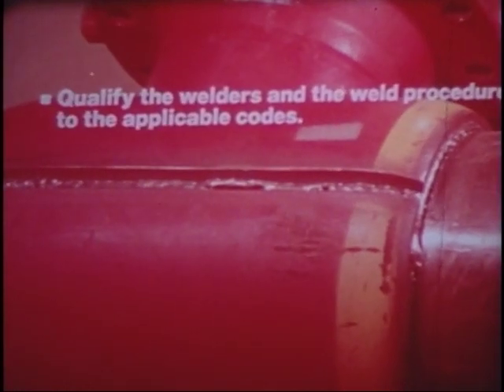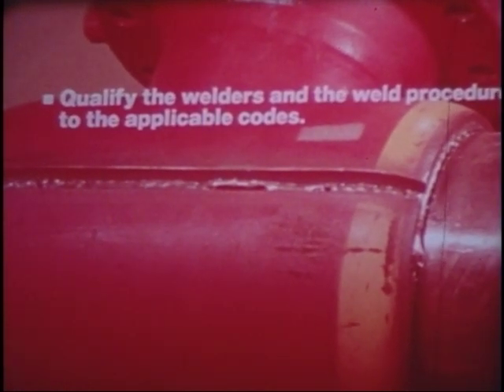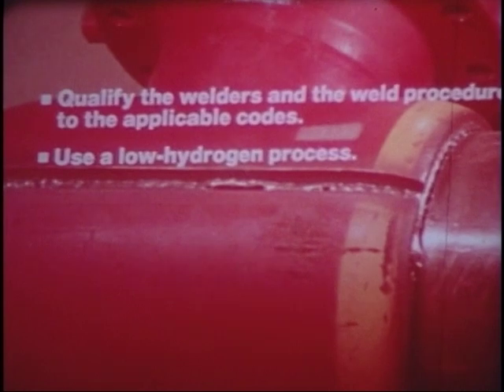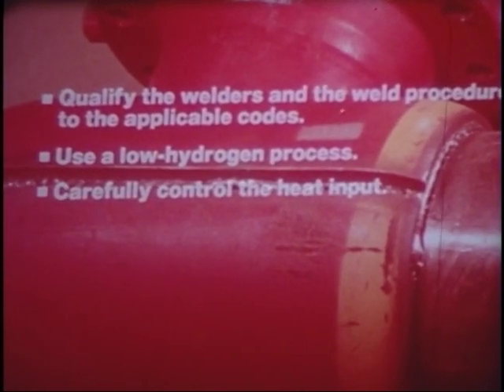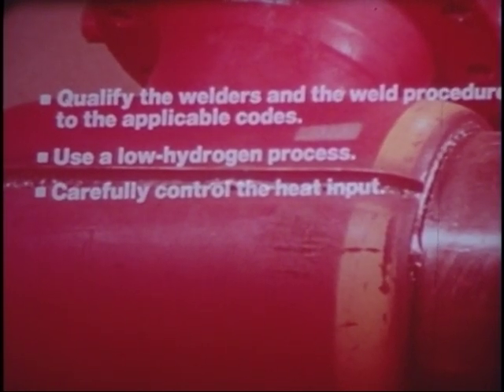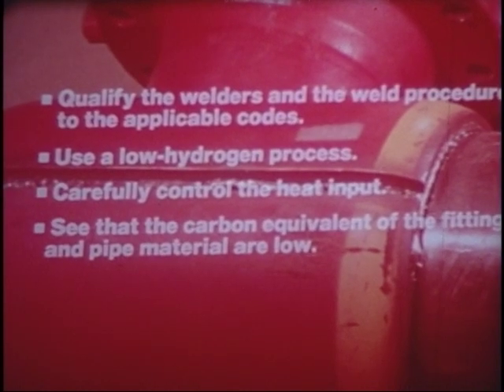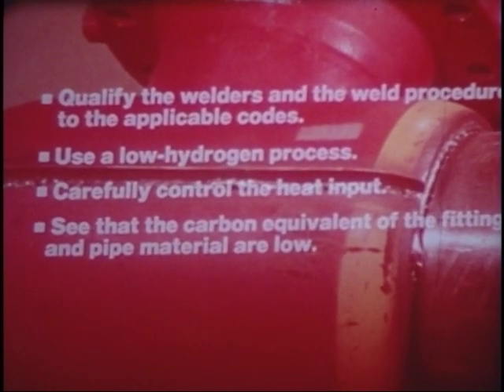Undercutting is the result of faulty electrode manipulation or the use of the incorrect size electrode. Improper current can also be blamed. To prevent these and other welding problems, such as porosity or lack of fusion, qualify the welders and weld procedures to the proper codes, use a low hydrogen process, carefully control the heat input, see that the carbon equivalents of the fitting and pipe material are low,